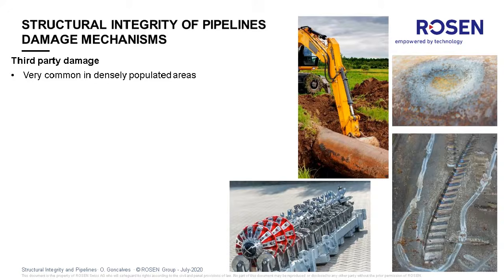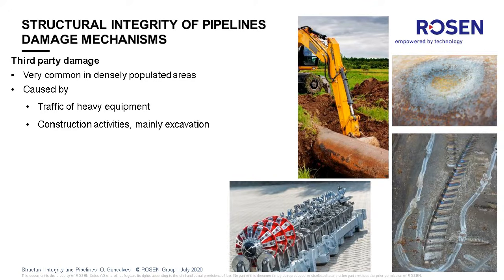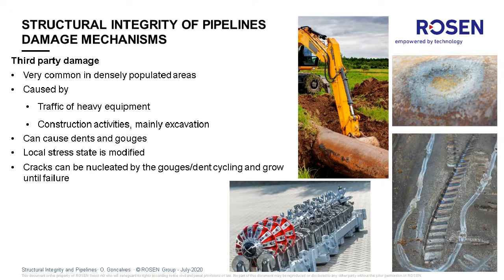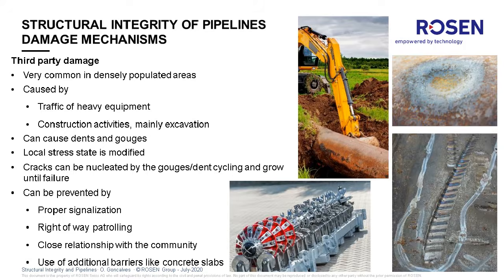Another type of damage mechanism is third-party damage, which is when something hits the pipeline and causes a dent. It can also cause a gouge, where there is also some removal of metal, and that gives rise to a different stress state. And because of the pressure fluctuation in the pipeline, that can lead to fatigue and failure. And then there is a specific tool, which is the caliper tool, that can also detect this kind of feature. It can be avoided with signalization, patrolling in the right of way, and even barriers to add another layer of protection to the pipeline.